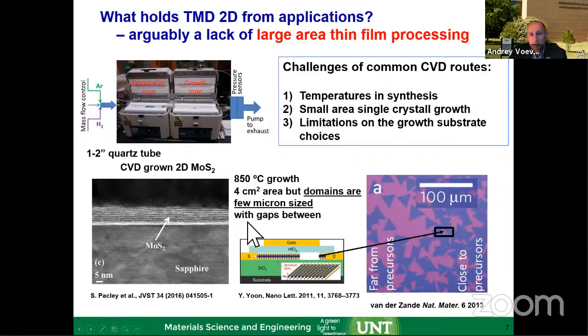So it is, but even now, when the community can grow fairly larger crystals, it's still a very high temperature growth. That means you cannot really put anything stretchable directly on the polymers. So yes, you have to do flexible material, but you are confined by the fabrication process to put them on something like a silicon wafer, something temperature stable, not directly on the polymer.